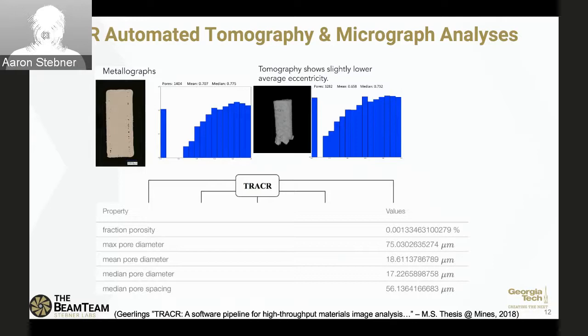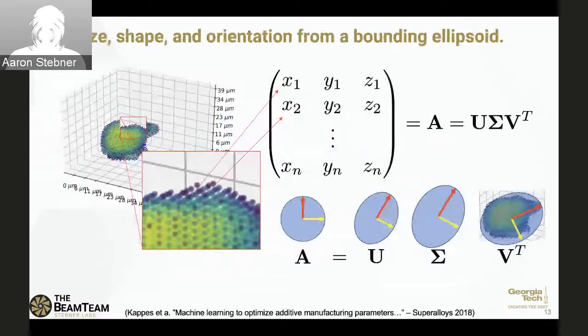And then more importantly, what we actually did was we used singular value decomposition on the data set, an algorithm to automatically calculate the three eigenvectors of each feature in the tomography. So instead of storing the visualization of the tomography, we stored matrices of every feature, its first three eigenvectors, as well as its position vector to the centroid of the geometry within the part. That gave us a matrix representation of each of the pores or inclusions or both within the part that we could then use for machine learning down the road. It was already put into matrix form for us. And if you go to the next slide.